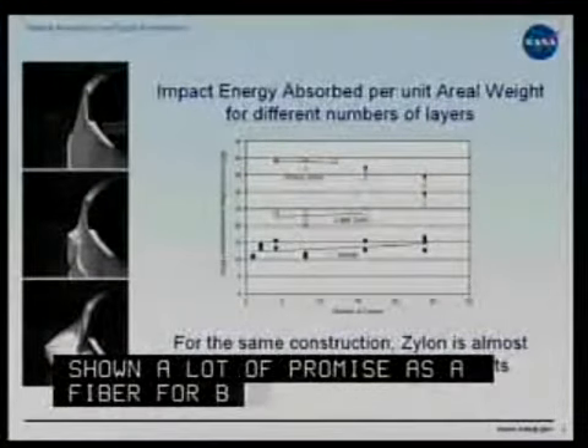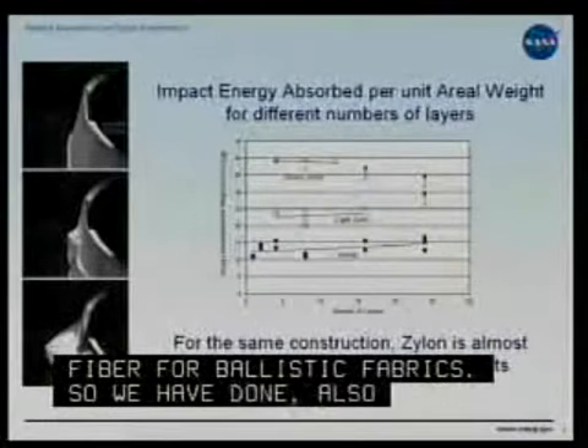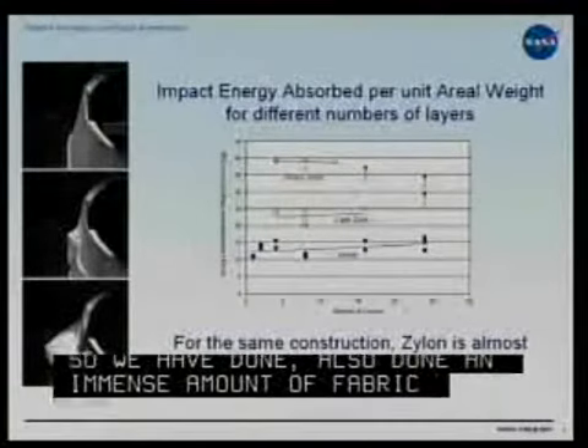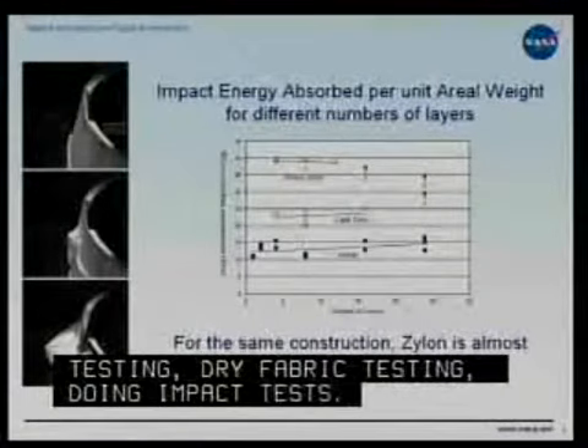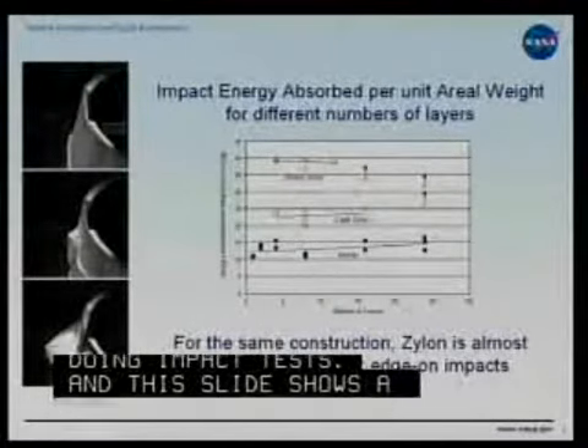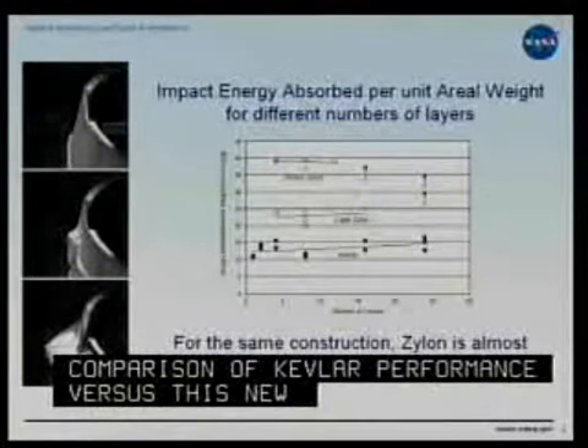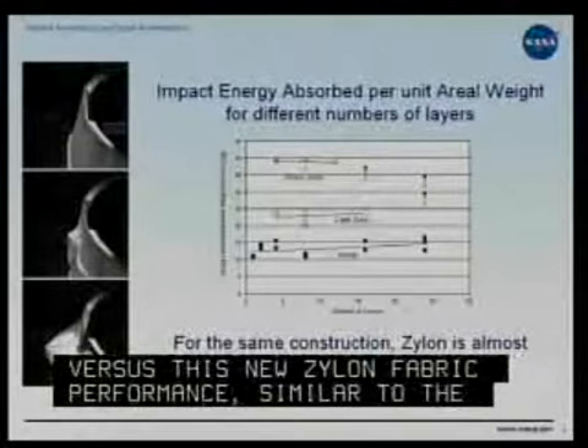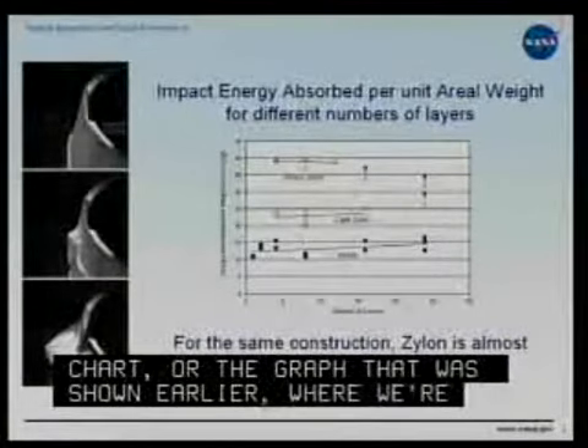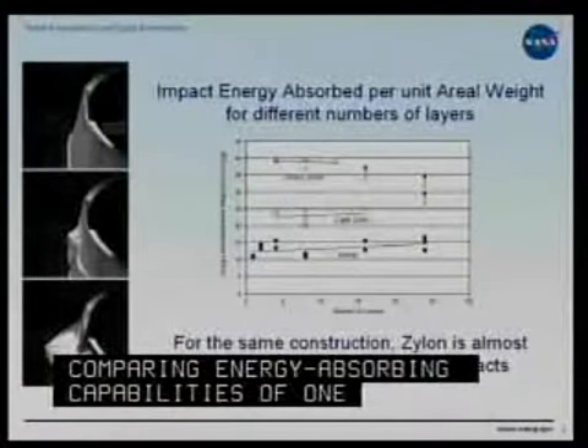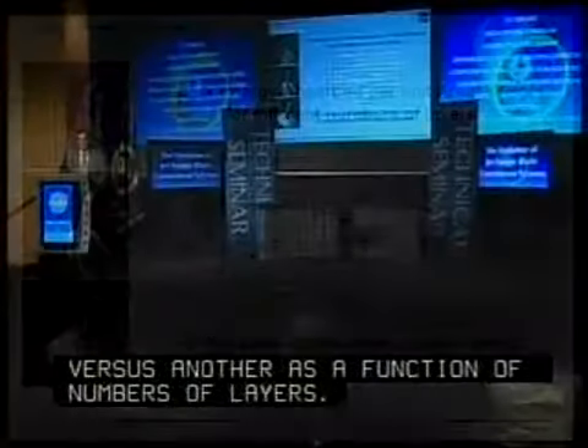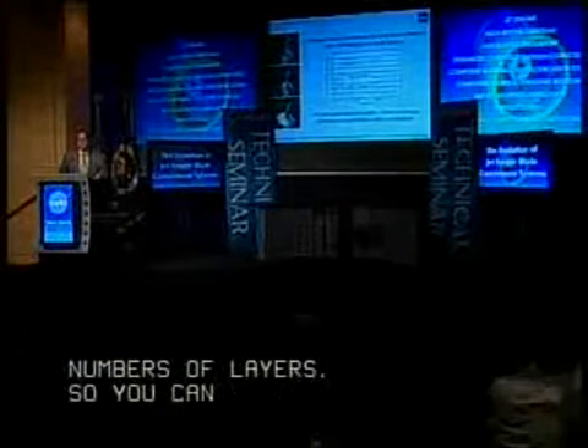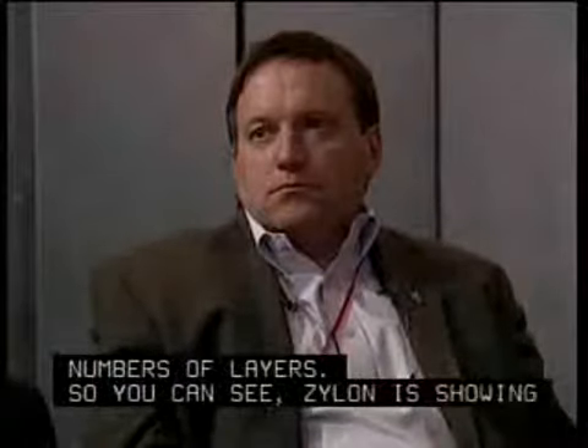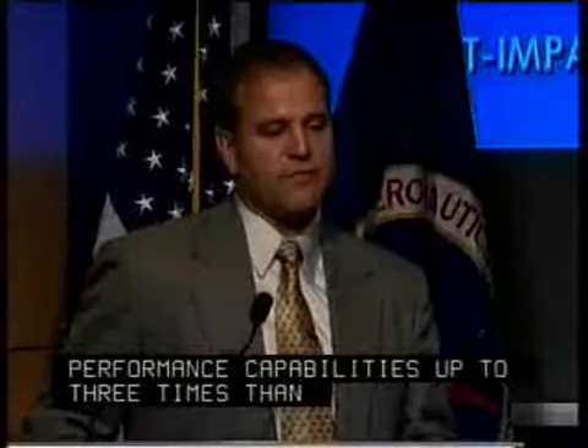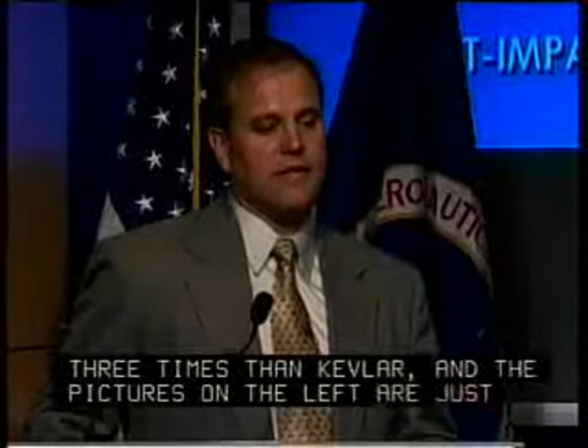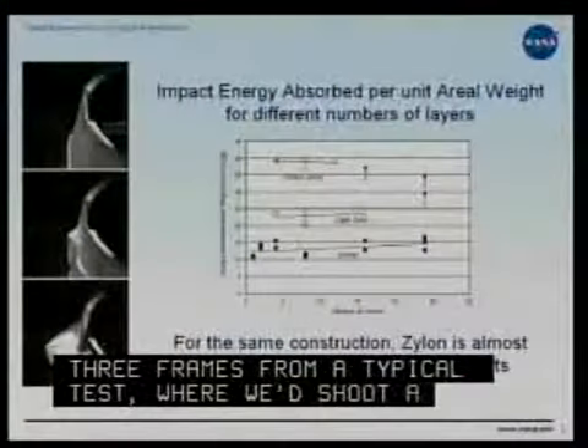So we have also done an immense amount of fabric testing, dry fabric testing, doing impact tests. And this slide shows comparison of Kevlar performance versus this new Zylon fabric performance. Similar to the graph that was shown earlier, where we're comparing energy absorbing capabilities of one fabric versus another as a function of numbers of layers. So you can see Zylon is showing performance capabilities up to 3 times that of Kevlar. And then the pictures on the left are just 3 frames from a typical test where we shoot a projectile into dry fabric specimens. So next slide, please.